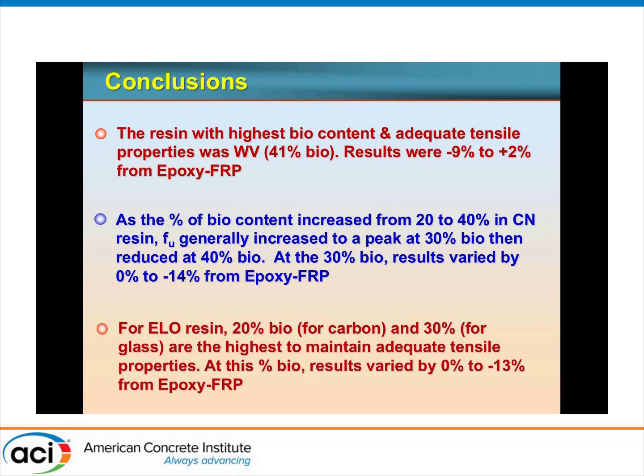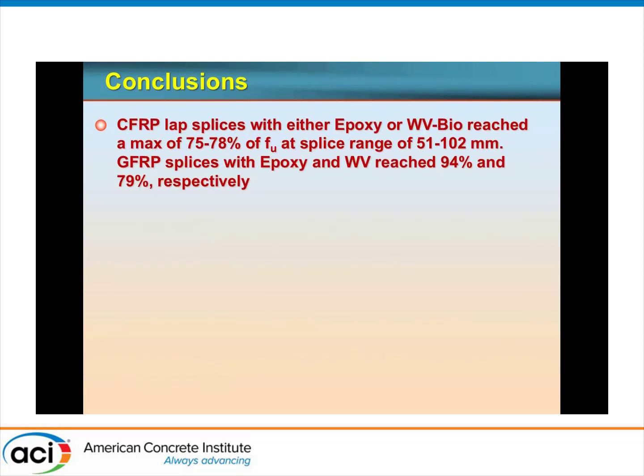For the ELO resin, that's the epoxidized linseed oil resins, 20% bio for carbon and 30% for glass are the most promising for this type of bioresin, providing adequate tensile properties. At these percent bio, the variations from reference epoxy were 0 to -13%.